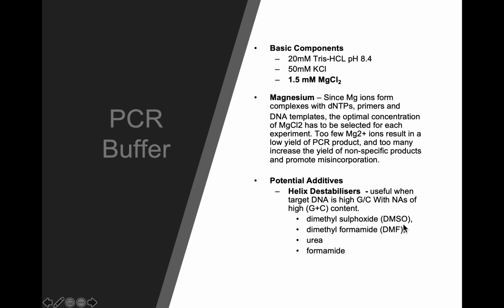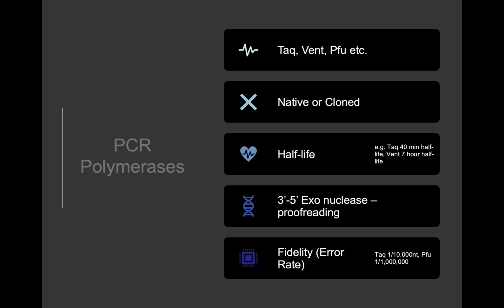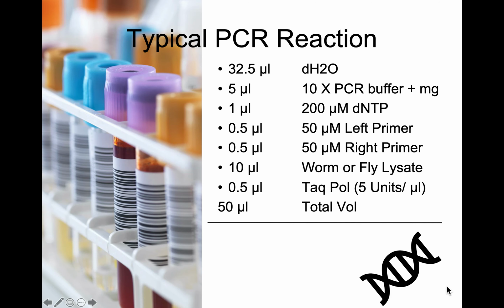Sometimes you add substances like DMSO, which is a helix destabilizer, and it helps to break up DNA with high GC content because guanines and cytosines are held together by 3 hydrogen bonds, so you have to break 3 bonds as opposed to breaking the 2 bonds of A and T. There are different types of polymerases that you can use, and they can be either native polymerases that can be found in nature like Taq, or they can be cloned or basically souped up polymerases. If you look at, let's say, the error rate of Taq polymerase, there's 1 error every 10,000 nucleotides, whereas for Pfu polymerase, you only get 1 error per million nucleotides. So it does matter which polymerase you use in your reaction.